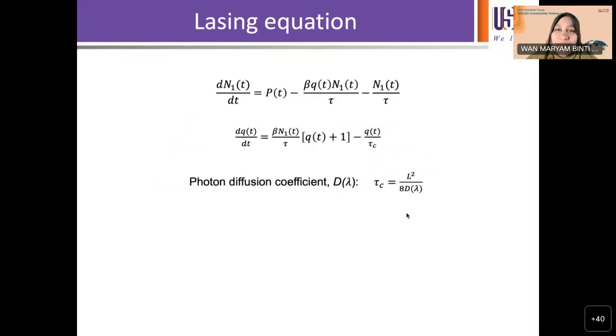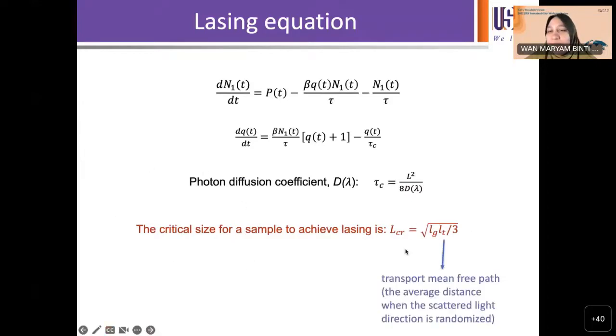Okay, and the rate equation related to lasing is the same as the standard lasing rate equation. However, we have something called the photon diffusion coefficient that we have to look at, because our photons are diffused inside and scattered, right? So there is a critical size that relates to the transport mean free path and the gain length. The transport mean free path is the average distance at which the scattered light becomes randomized. Okay, so it relies on these two parameters mostly.